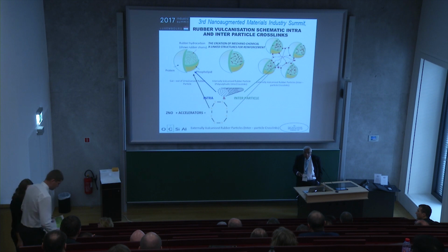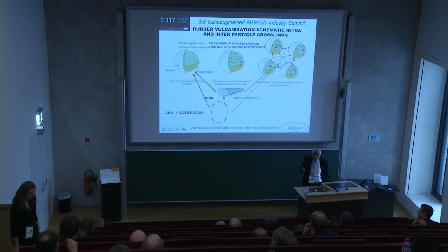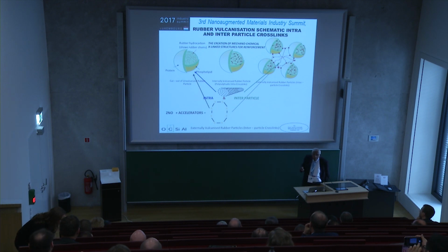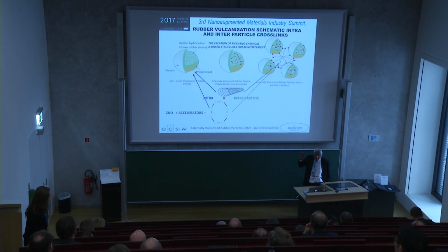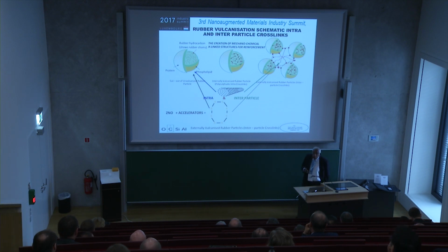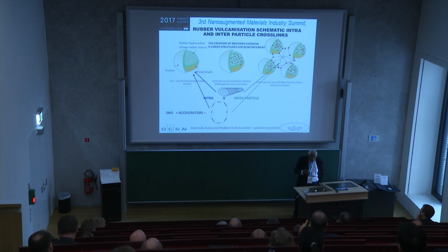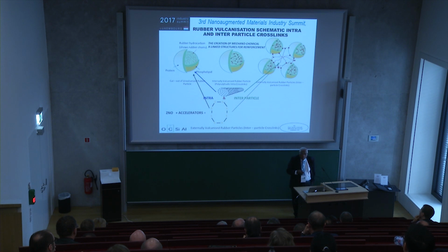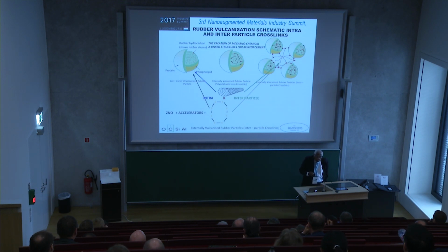So we have two types of action here. We are looking at the intra-particle penetration of the chemicals and also of the CNT, and we are looking at the interparticle reactions between the particles as the film dries down. It's important that in dry rubber, carbon black reinforcement is due to the formation of structures, bridges, which are agglomerates, which give you a mechanochemical crosslink in addition to the purely chemical crosslink. It's the same principle that we are trying to create here, where the agglomerates act as bridges between the entanglements of the natural rubber particle. Natural rubber has a very high molecular weight, I think about 1.5 million, much higher than most normal elastomers. So these are all very long chain cis polyisoprene molecules.